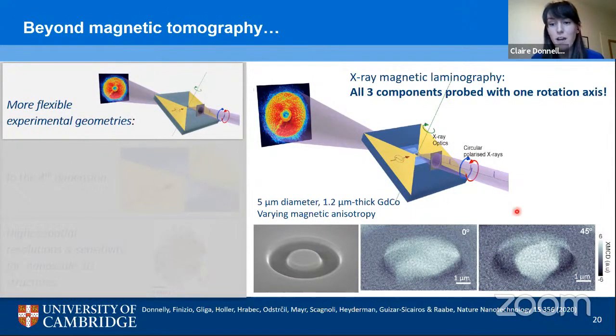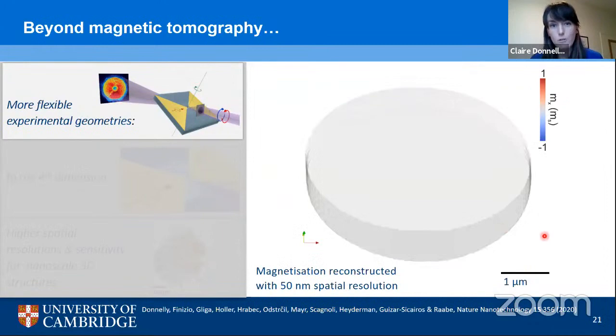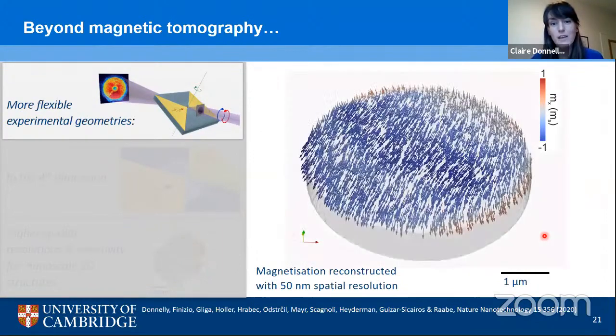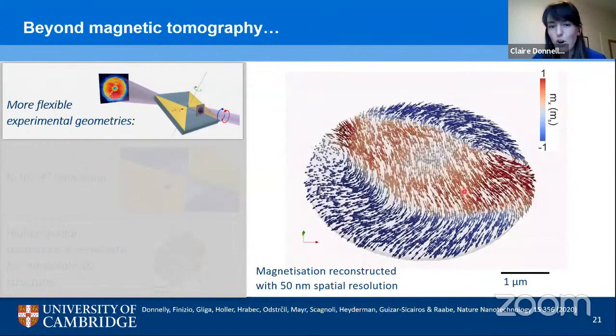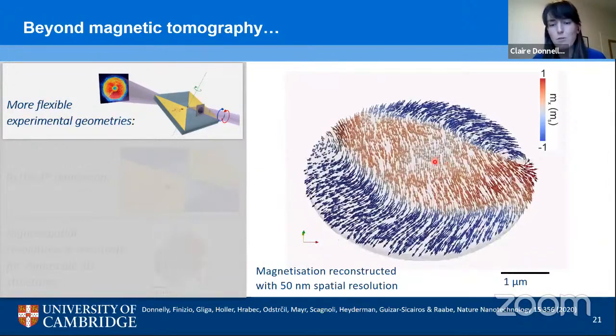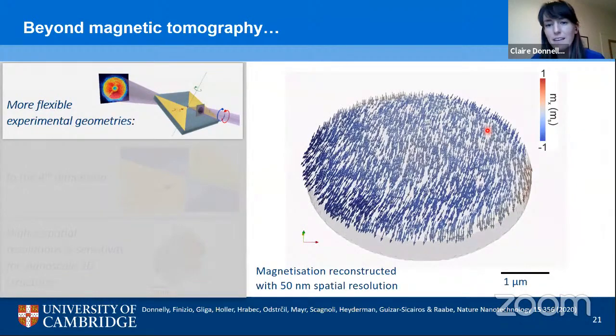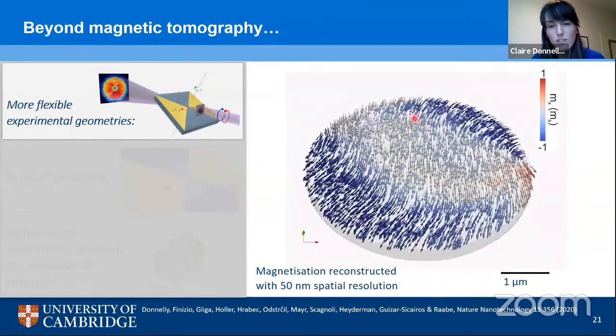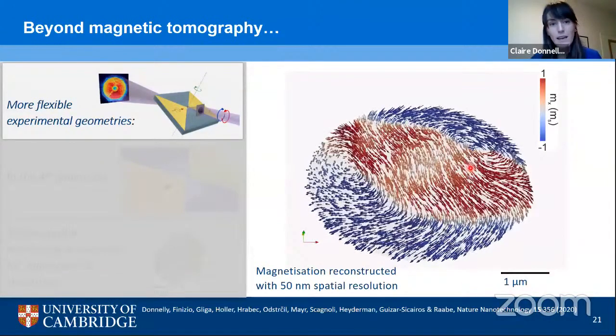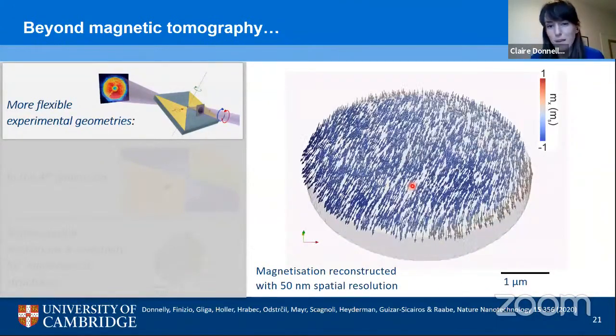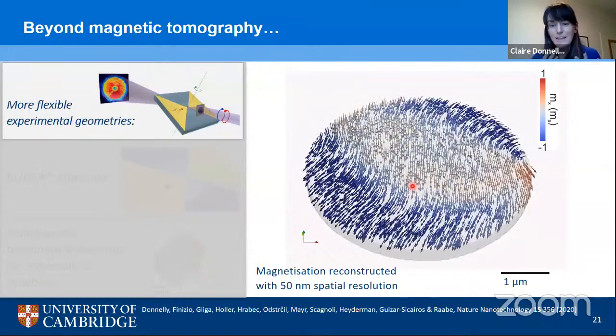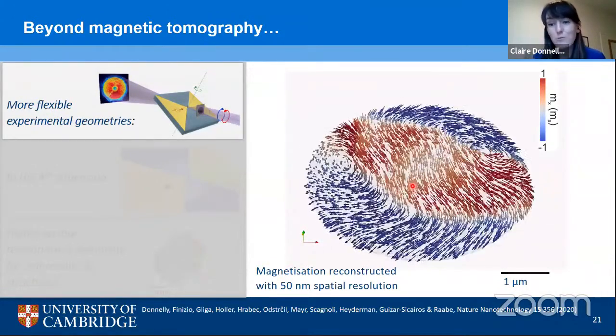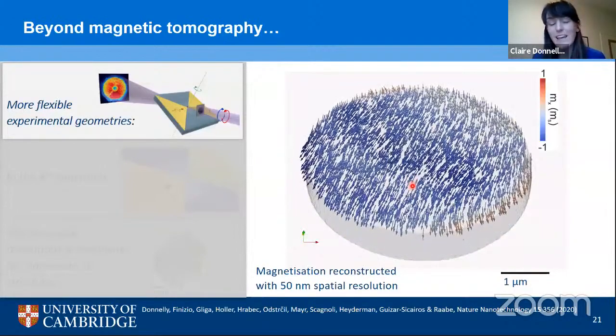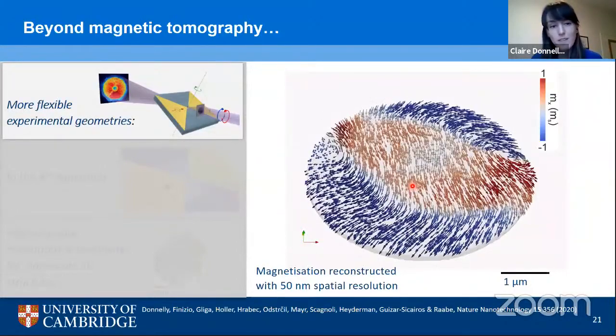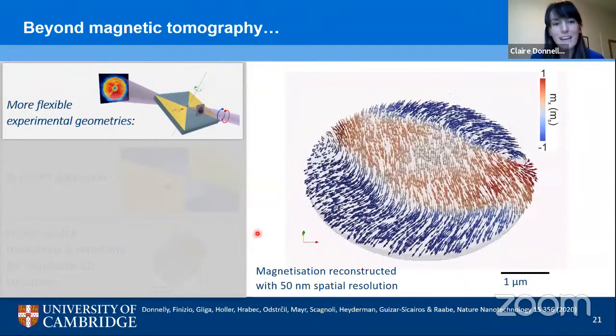And so we measure 144 of these projections around 360 degrees and use our newly upgraded reconstruction algorithm to reconstruct the internal magnetic configuration of our sample. So we see a smooth transition between a single uniform domain at the top of our structure, to a double vortex state at the bottom, indicative of this change in magnetic anisotropy. And this is a really nice example of what we can do with laminography. And indeed with our simulations, we see that laminography works incredibly well for 3D magnetic imaging. And it actually has yet another advantage.